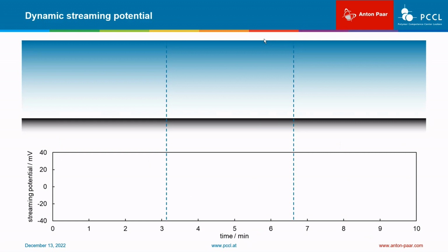The monitoring of liquid on solid surface adsorption processes, a feature which is especially enabled by the surface Zeta potential analysis through a dynamic streaming potential measurement, is another mode of measurement. For recording adsorption kinetics, we measure the evolution of the streaming potential with time, thereby varying the composition of the aqueous sample simultaneously. We start with the recording of a baseline for the streaming potential of the sample, rinsed with a buffer solution at a constant pressure and a constant flow rate.